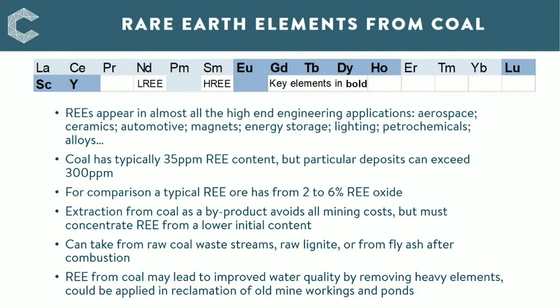The rare earth content in coal is much less than for ore deposits, but can be over 300 ppm. The issue then is the cost of concentration compared to full mining and refining of ores that normally contain between 2% and 6%. So the first target set for this program was to achieve a 2% content of rare earth elements. And thinking about taking rare earths from rock coal or coal wastes, or after combustion from fly ash, then the main issue is whether the rare earths are with the organic or the mineral fraction, and the effect of the combustion conditions on the rare earths.